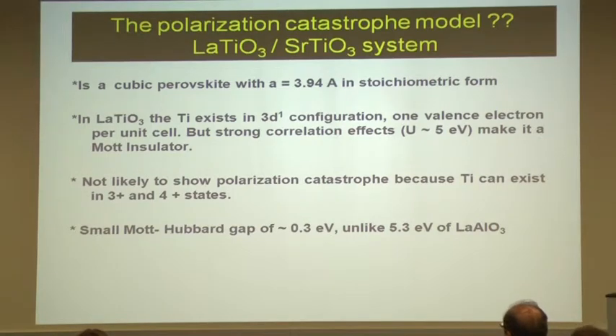Now, this is all that has been done. A lot more has been done on the lanthanum aluminate strontium titanate interface. We wanted to take a different path because we wanted to actually address this issue of polarization catastrophe and also a little bit of Mott physics. So we took this material, lanthanum titanate. And lanthanum titanate is a cubic perovskite with a lattice parameter of 3.94 angstroms, has a perfect lattice match with strontium titanate.